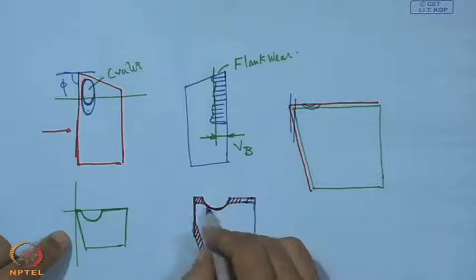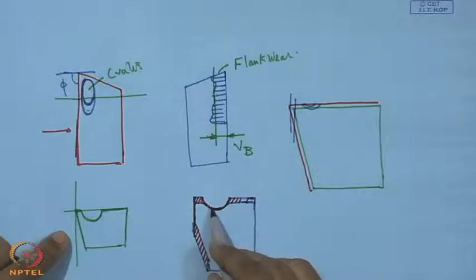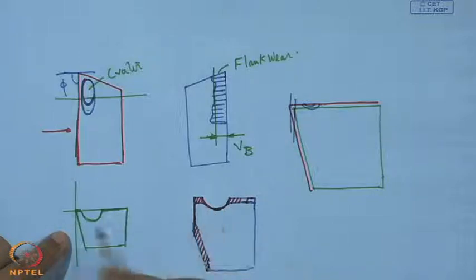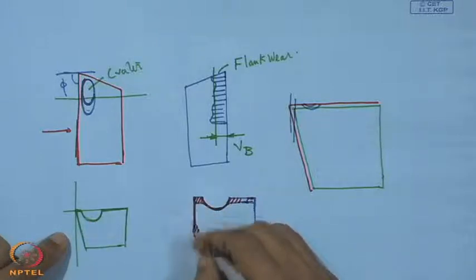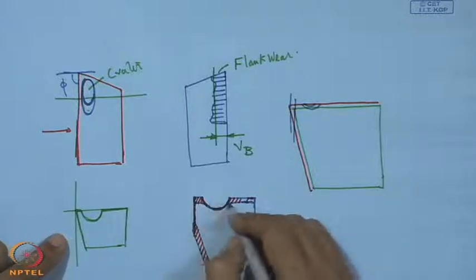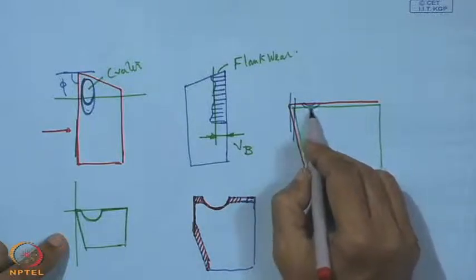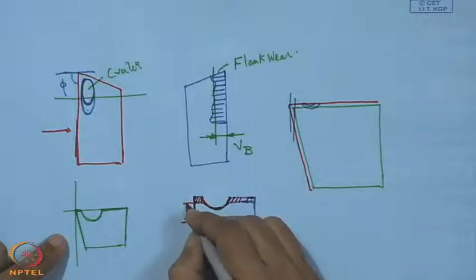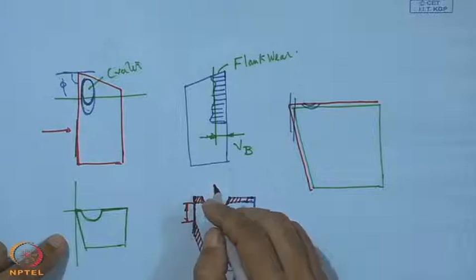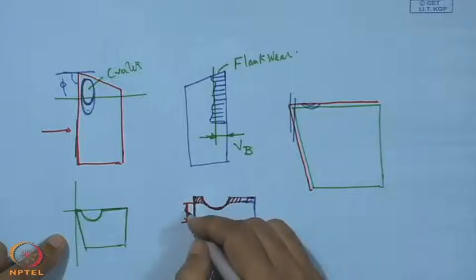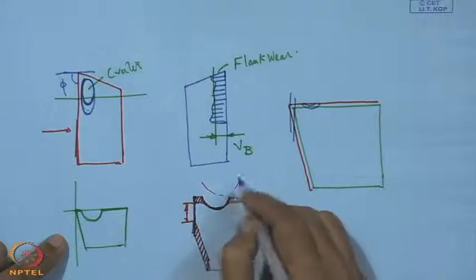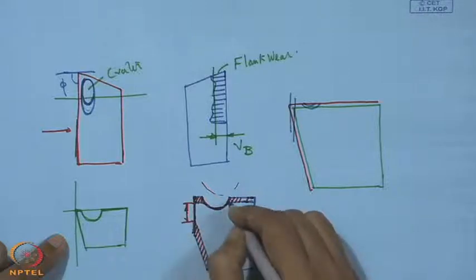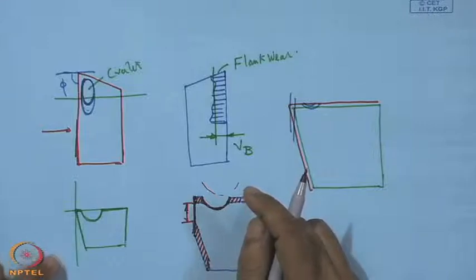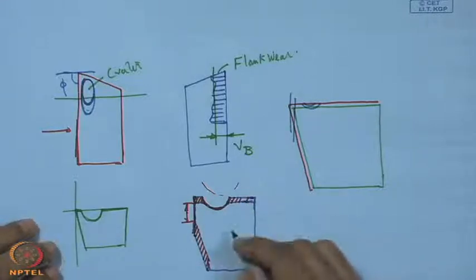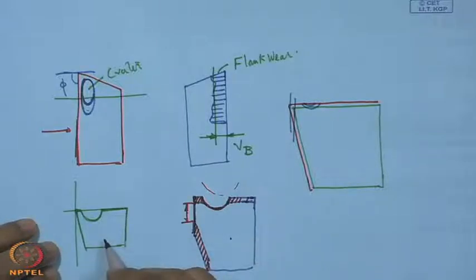However, this tool with such formation can still hold the wear rate much slower compared to an uncoated tool, for the simple reason that these two edges and these two edges will act like wear pads. So, with this wear pad, though coating is removed from the center of the cavity or from this zone of the flank, since we have two edges which will support this tool, in direct contact with the machined surface, and here with the chip, these two wear pads on the flank and on the rake surface will still control the growth of the crater. So, the wear rate of this particular tool will be less compared to that uncoated tool.